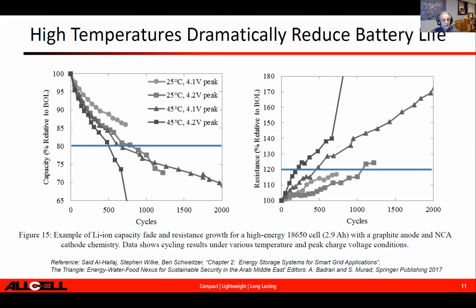And also even the slightest change of cutoff voltage, for example, if you go from 4.2 volt to 4.1 volt, which is, instead of doing 100% state of charge, you go to 90%, you start also seeing significant improvement in life. And the graph to the right shows you that that's mainly because of the increase in impedance, or what's called resistance. And that's the main culprit for a lot of the challenges for battery performance and cycle life. We've done a little bit of work on that.